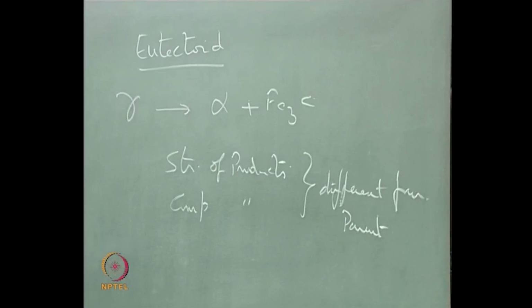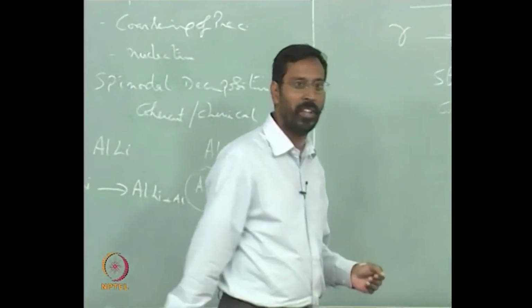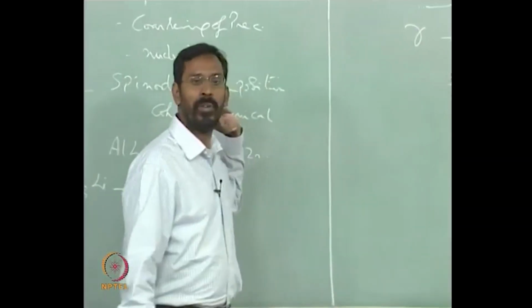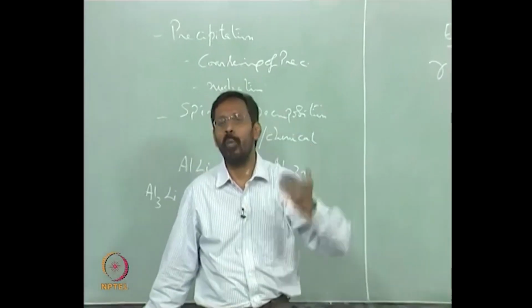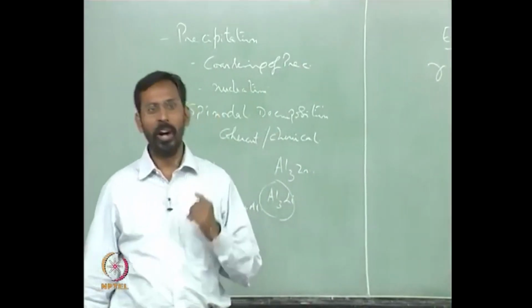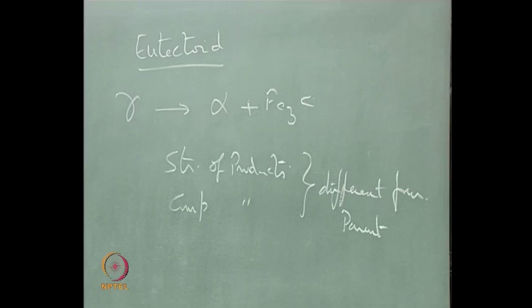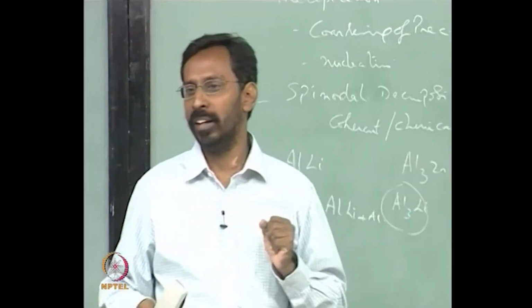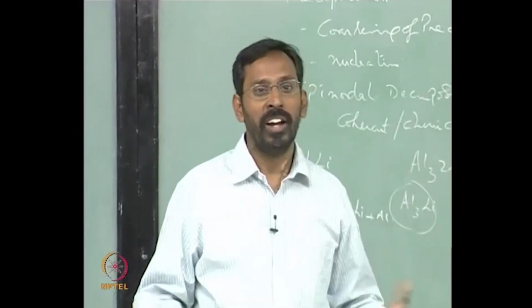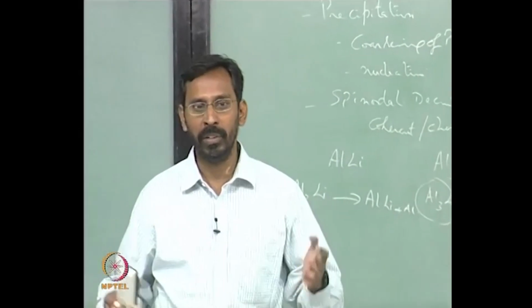The moment you have this situation, obviously you will know that the activation energy for such a transformation is going to be higher, isn't it? So when compared to a normal precipitation, you would see that this is more difficult. So that means you need more undercooling, and so obviously that means if you talk in terms of precipitation, the system tries to avoid going through a process of higher activation energy by choosing something which has a lower activation energy. That is where transient phases come into picture, GP zones and things like that.